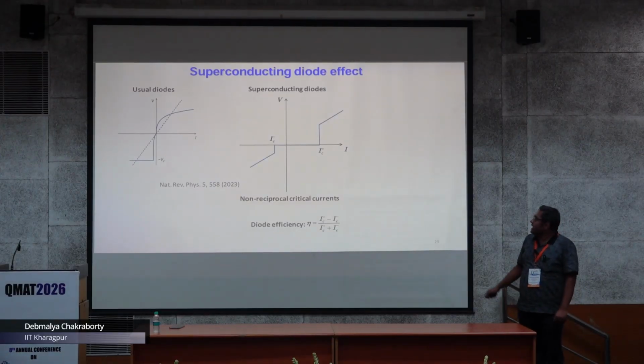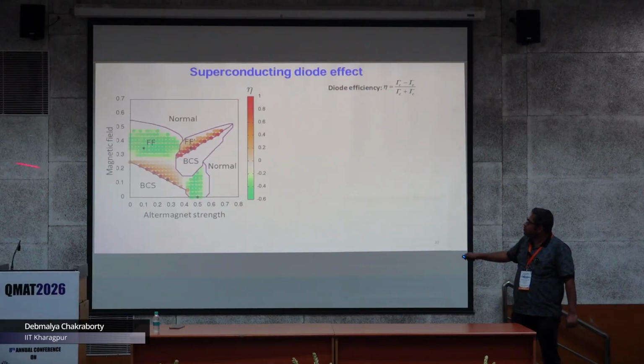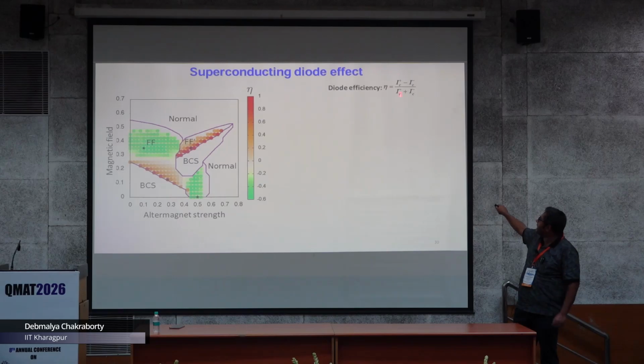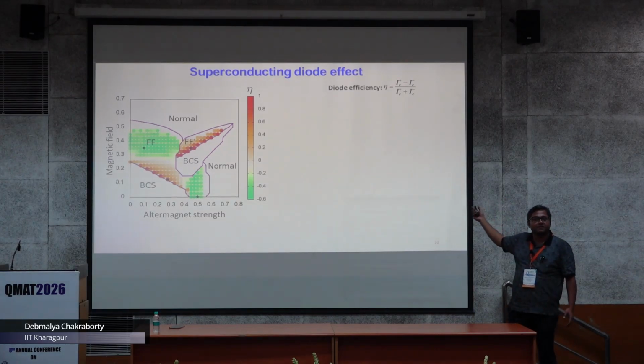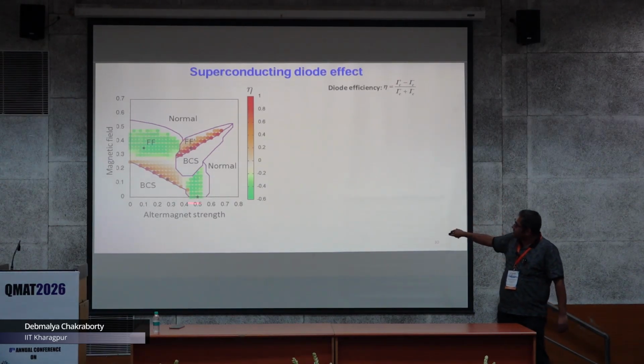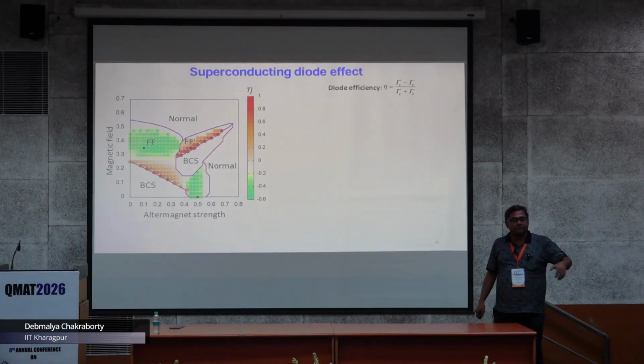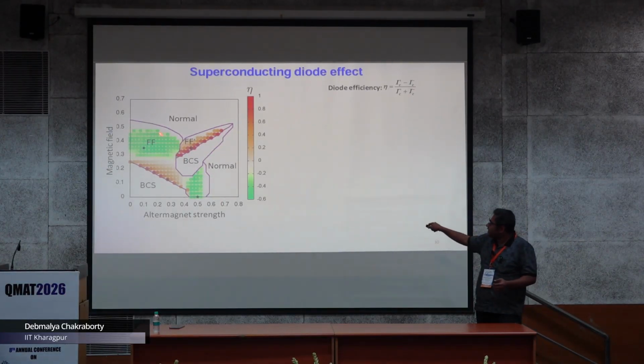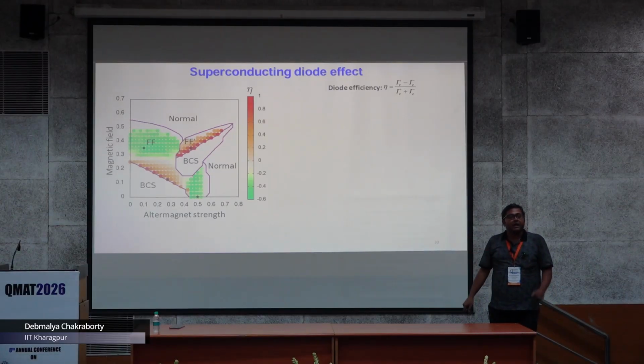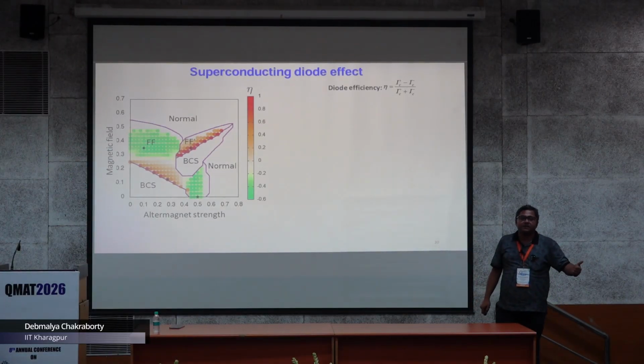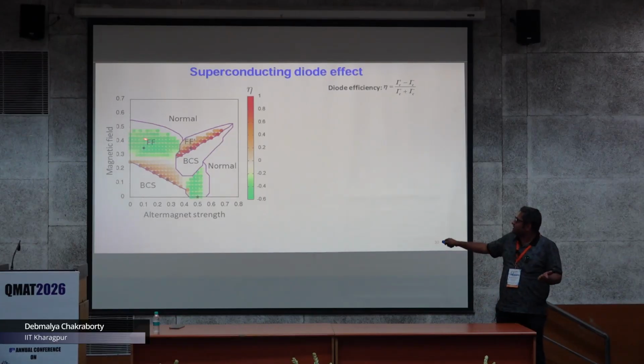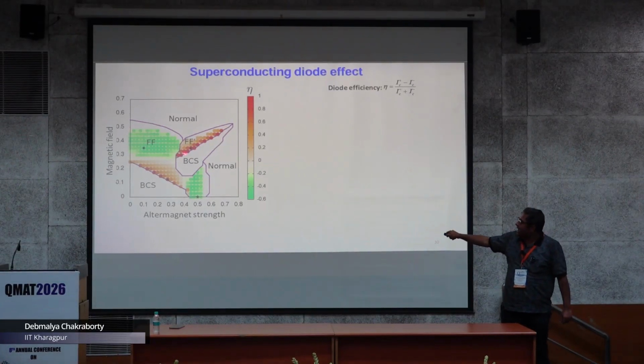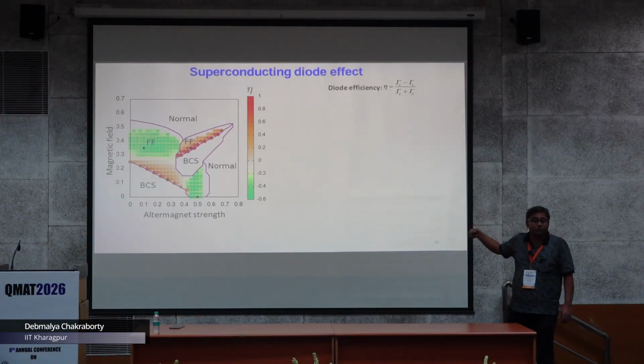Now to look at the diode efficiency in the same case that we have calculated, we look at the same phase diagram, but the color now indicates something else. The color is the diode efficiency, IC plus minus IC minus by the average, and if you look at the efficiency, the superconducting diode effect is there only if you have finite momentum superconductivity, because this FF state actually breaks the inversion and time reversal both. As a result, you will have this diode effect. And if you look at the efficiency, these are multiplied by 10, 100 to get the efficiency.